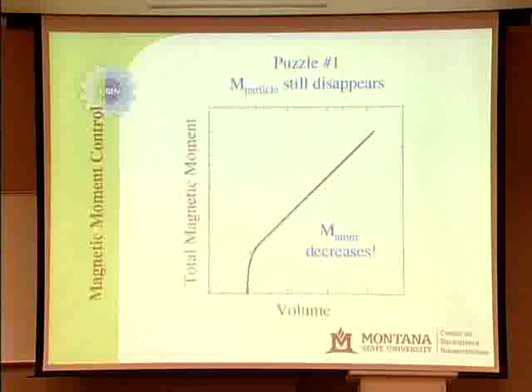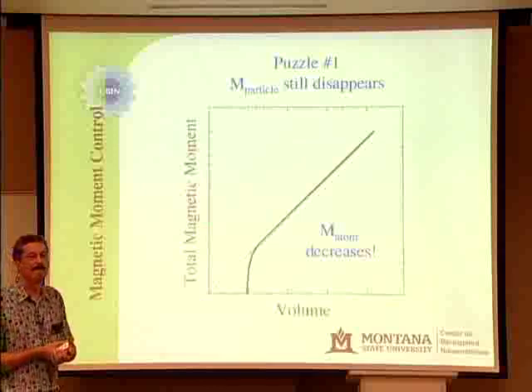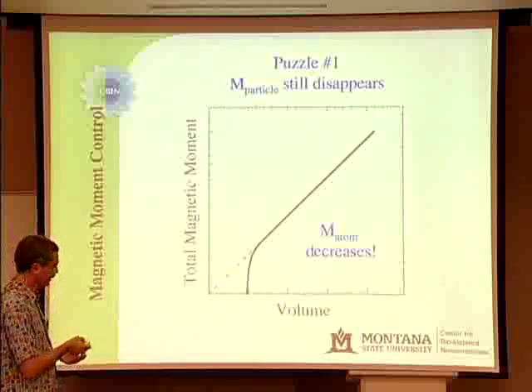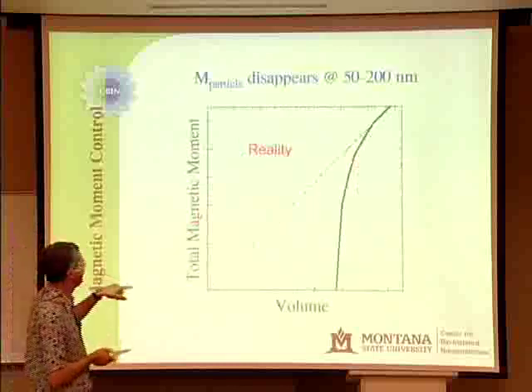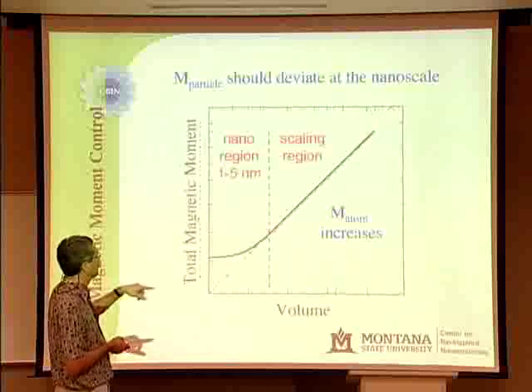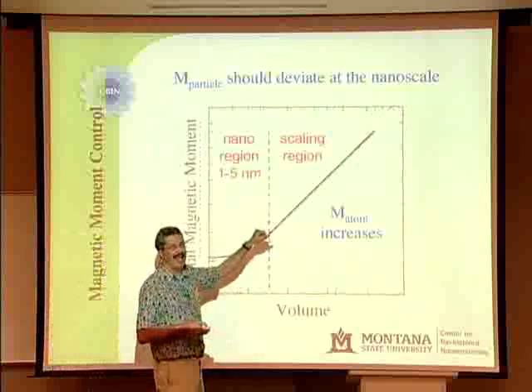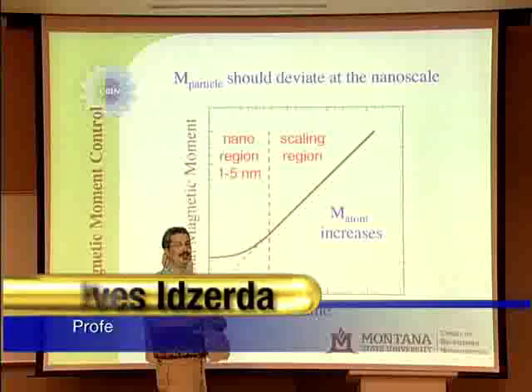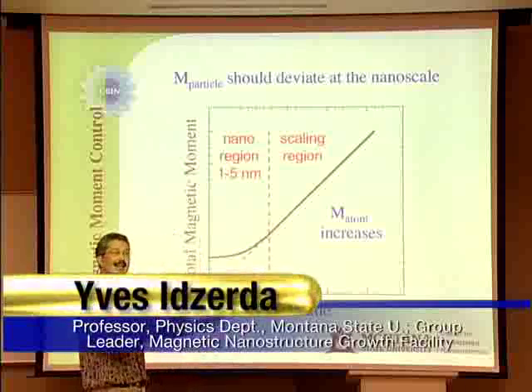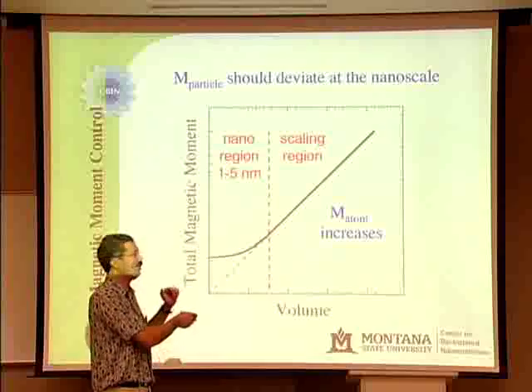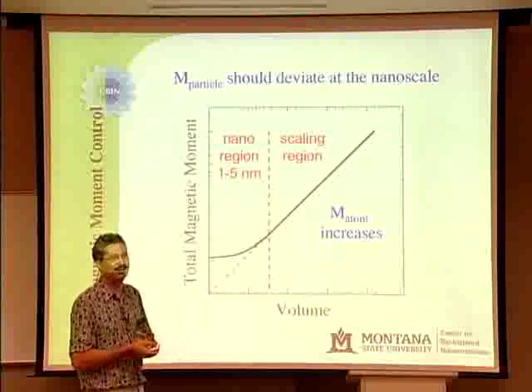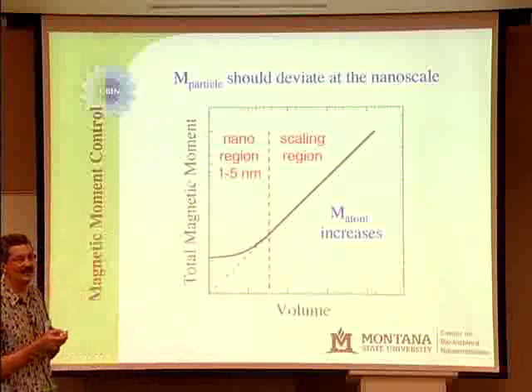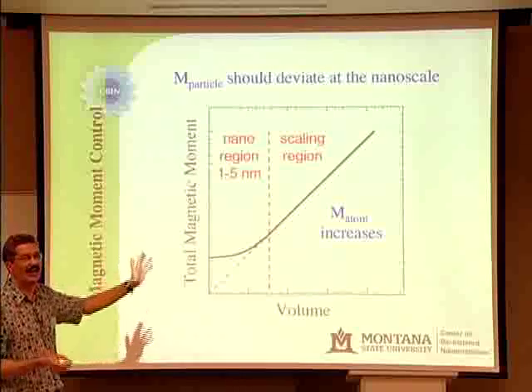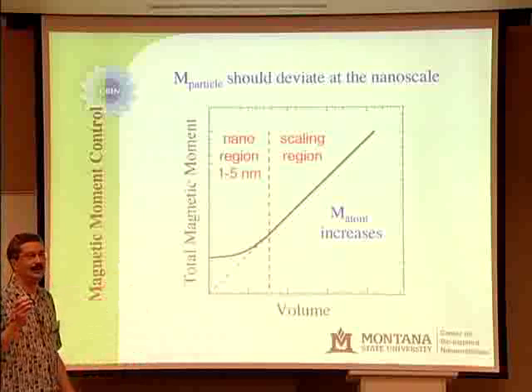Go ahead. It seems like if you have more atoms, the fields would add together and you have a stronger dipole. So the idea here, if I just back up a couple, was that if I just took the theory picture that we had from the beginning, and put more and more of these atoms together, the fact that they're in a magnetic field would give me more and more moment. Is that what you're saying? Right. So our measurements are always made in a big magnetic field. We stick it in our big magnet in the lab. So we get around the problem of something called the demagnetization field that might be present in these samples. So this is the maximum moment I could get out of it if I applied a big field to it. Okay? Hopefully that answered that part of it.